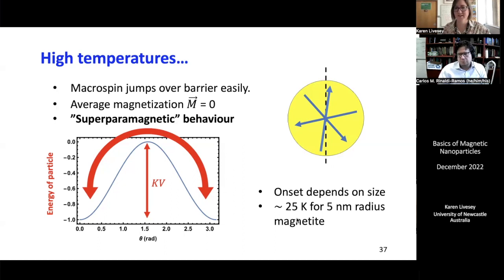I've done a quick estimate. I hope it's correct. I've got for 5 nanometer radius magnetite, this occurs around 25 Kelvin, okay, to give you a feeling. So if we're at room temperature with these particles, they really are superparamagnetic. But if we can cool below 25 Kelvin, then we see a net moment reappear.